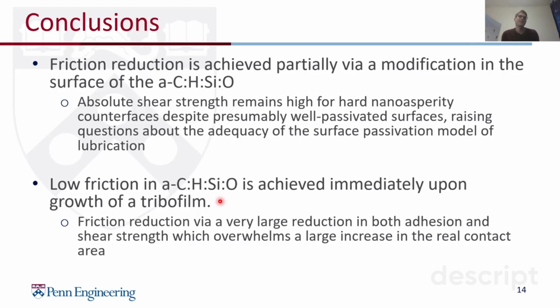So just to conclude here, the friction reduction that we see at nanoscale is at least partially due to some modification in the surface of the silicon oxide doped hydrogenated amorphous carbon. And we think this is at least part of what happens during the run-in process in macroscale sliding experiments. And additionally, we see in the nanoscale experiments that the absolute shear strength remains very high. So this is, despite the fact that this is presumably a well surface passivated surface, we see high shear strengths nonetheless.